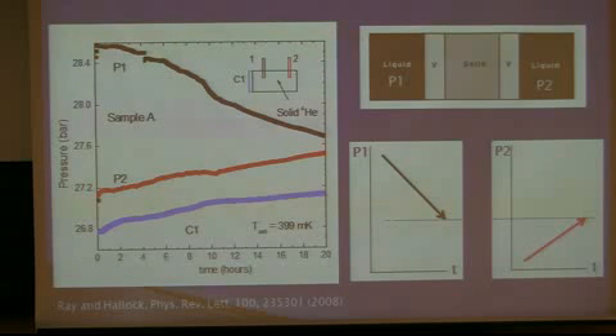Okay, this is very different from viscous flow. In viscous flow, the flux will be determined by the pressure gradient. That's why the time dependence must be exponential if it is viscous flow. So this kind of linear time dependence is actually characteristic of superfluid. The flux is only characterized by the critical velocity. Okay, so this is one example of superflow published in Phys. Rev. Lett..